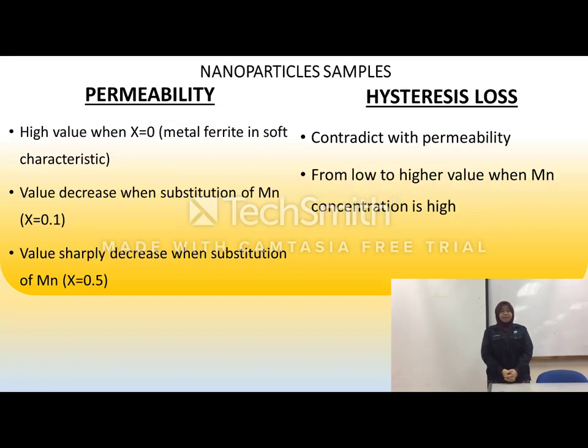Okay, so for the nanoparticle samples, the permeability will have a higher value when the concentration x is equal to zero, whereas the metal ferrite is in soft characteristic. And the value will then decrease when the substitution concentration of manganese is equal to 0.1. And the value will sharply decrease when the concentration of manganese is substituted with 0.5. While the hysteresis loss is very contradictory to permeability. It will go from low to higher value when manganese concentration is high.